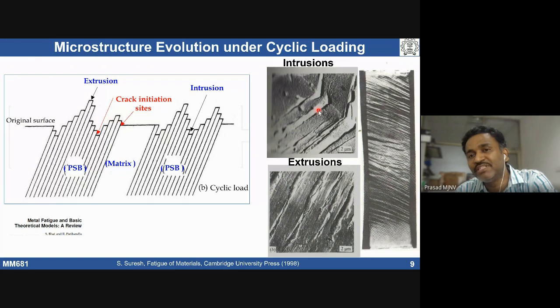The valleys are basically called intrusions. The cracks we are seeing are like valleys. These are called intrusions. And what we see as hills are called extrusions. Formation of intrusions and extrusions is also because of cyclic slip activity. This is another characteristic feature we can see during cyclic deformation of a material. Is it clear?